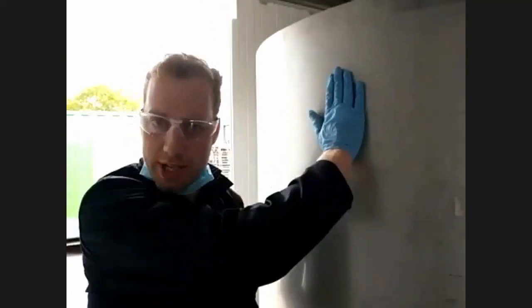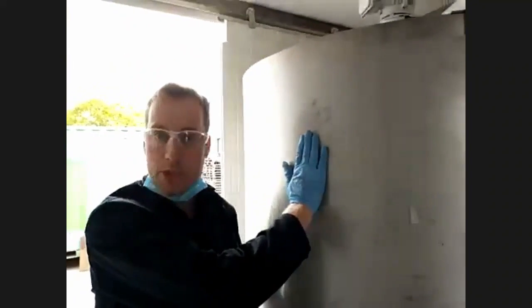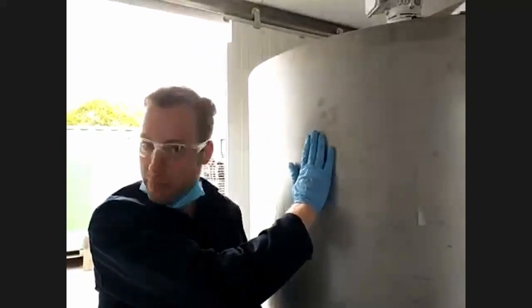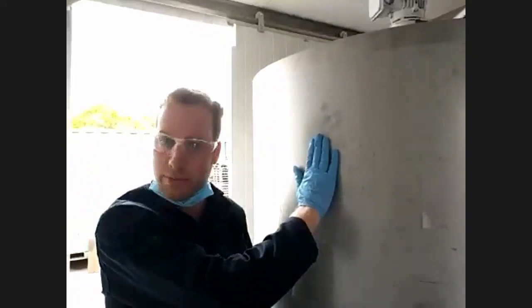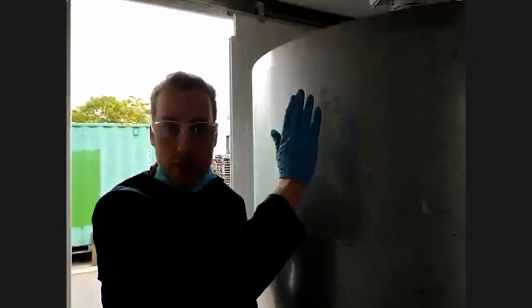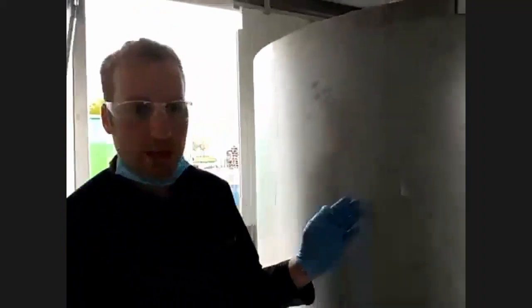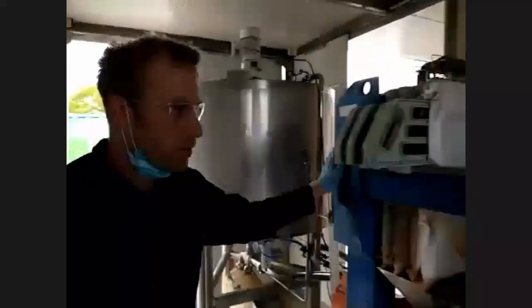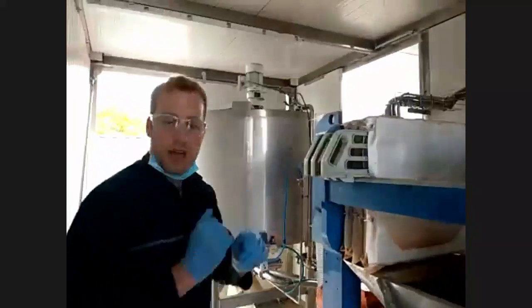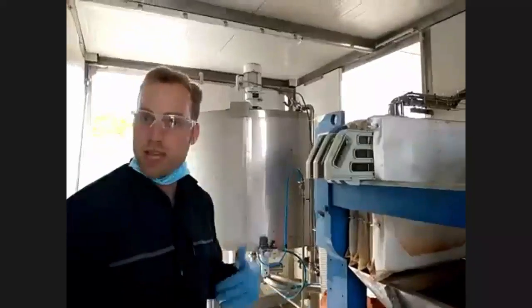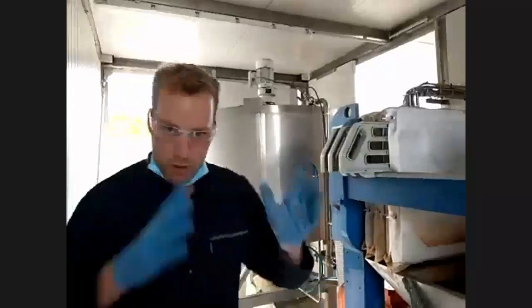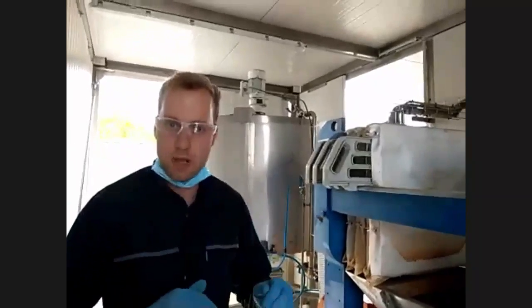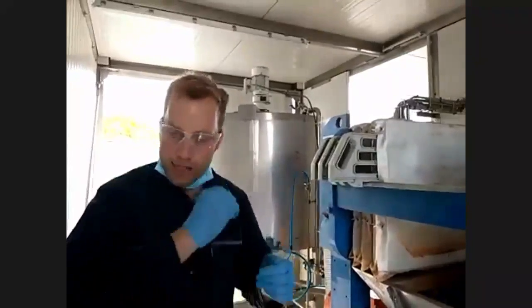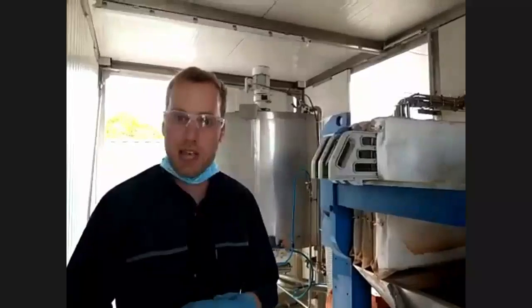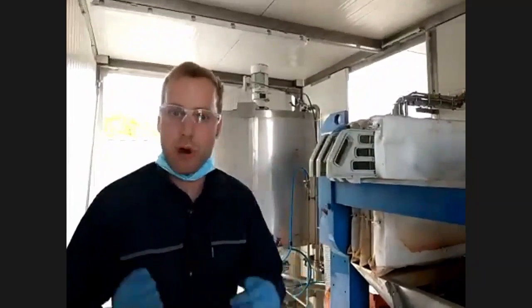So the red mud comes in from outside, it goes into this tank. It's a double layer tank, so you can heat up the temperature, which can be very nice, for example, for alkalization, dealkalization. Then it goes to this filter press. So the solution is pressed out, and the solution can be recovered, for example, to make inorganic polymers. Then the dry material falls out in a screw mixer. It is a bit broken up, and then it can get transported and pelletized into a very nice product. And I will show you now how the mixer works.